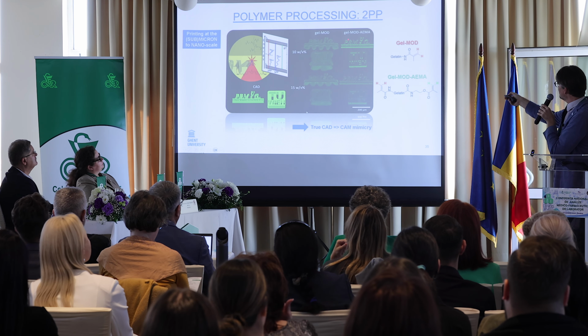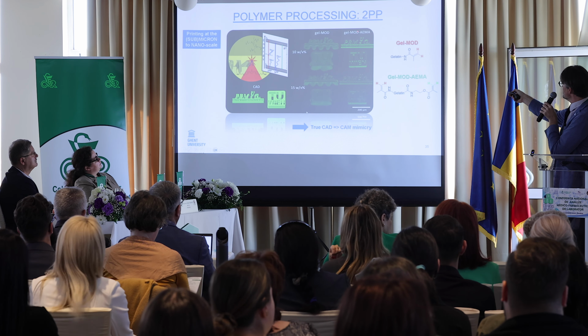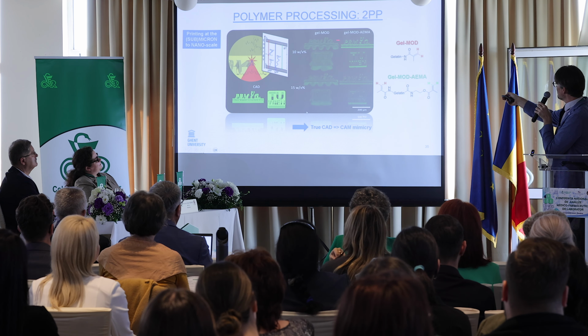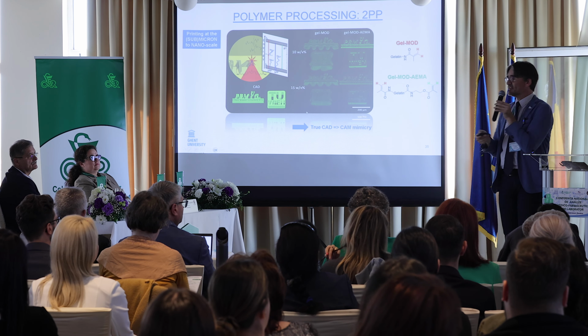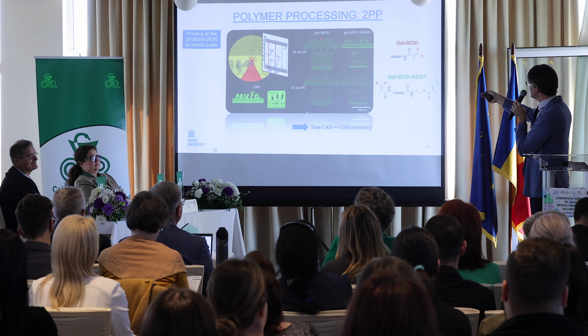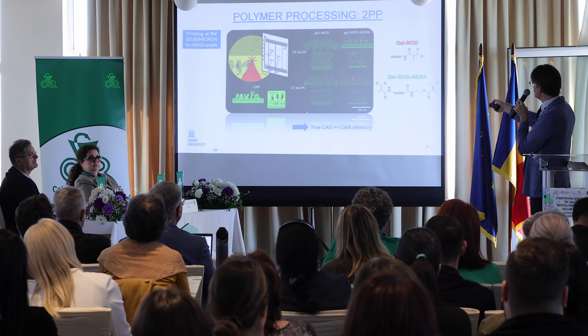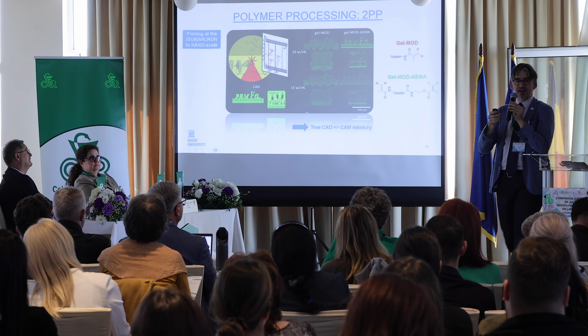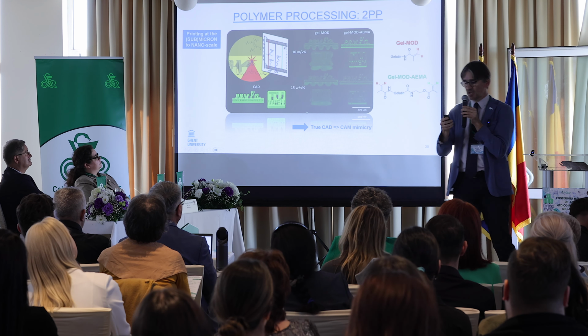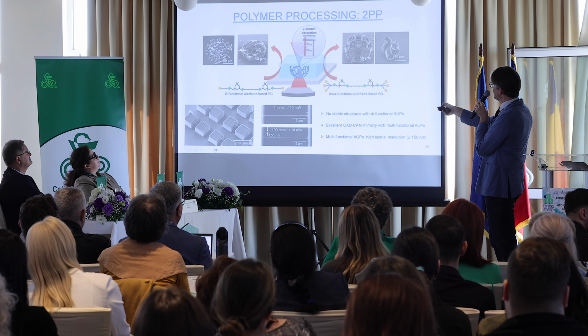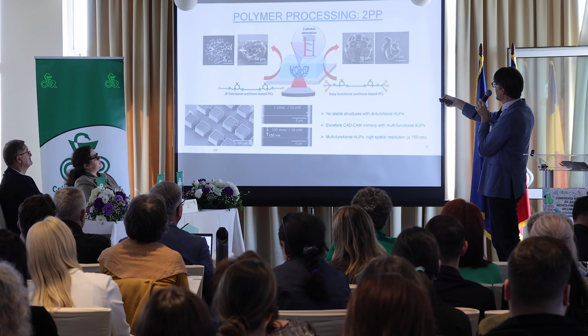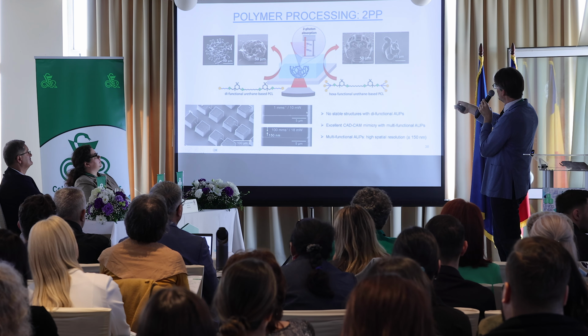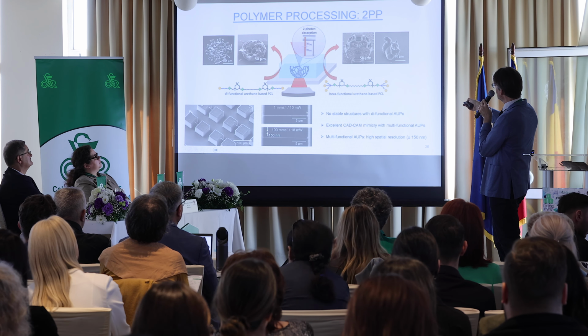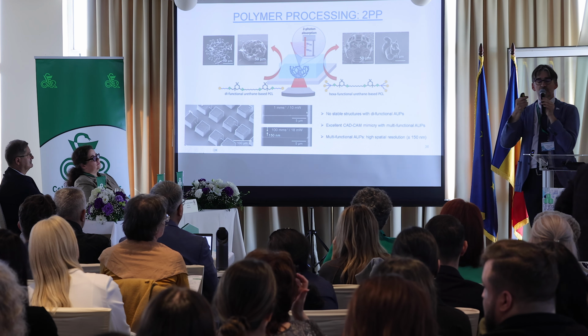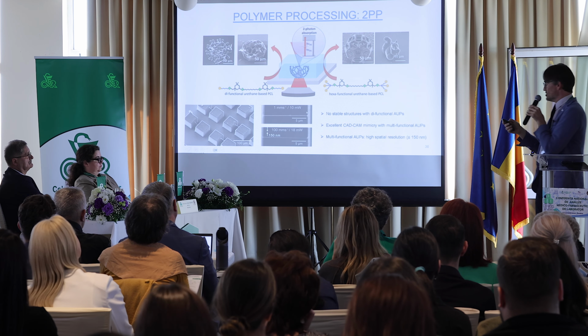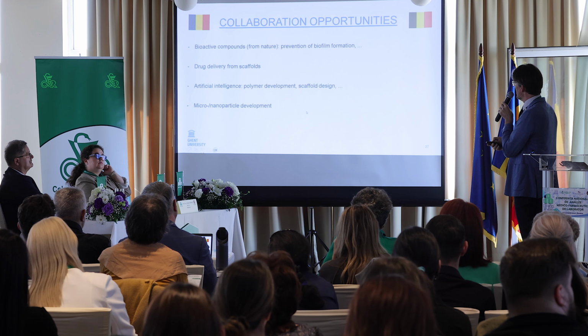But what I want to show here on the left and the right is, and that's for a different type of polymer which we also apply in our lab, that by very small variations in chemical composition, we actually go from polymers that cannot be printed at all using two-photon polymerization to polymers here on the right, which enable a very precise mimicking of the original design of the material, and completely similar data were obtained with our AUPs. Certain polymers cannot lead to stable structures. If you increase the number of functional groups at the end of each polymer, then all of a sudden the polymer scaffolds that you obtain are stable structures to be further applied.